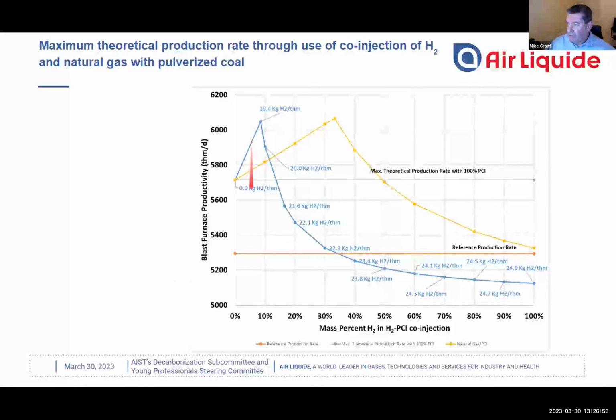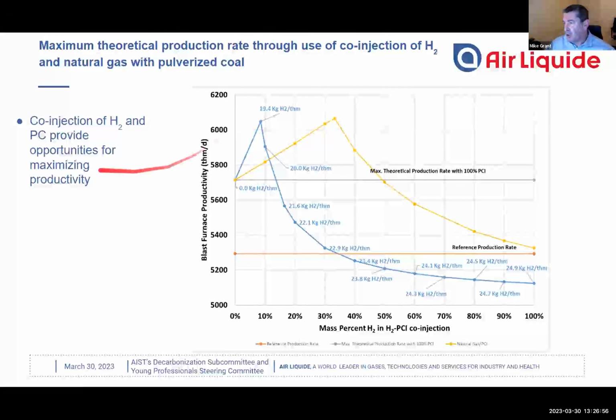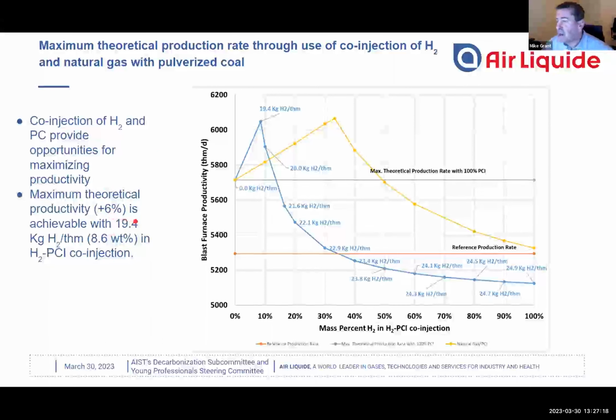However, there is a productivity benefit, and you see if we co-inject PCI with hydrogen, we can actually increase the productivity of the blast furnace beyond the limitations of the original operation with PCI. So if this is the maximum theoretical production rate with PCI, and we mix a little bit of hydrogen in there, we can actually get another 6% increase in productivity on a theoretical basis. The same effect is also true with natural gas, although you need a higher amount of natural gas in order to get this maximum productivity benefit. But nevertheless, there are some benefits to co-injecting hydrogen and or natural gas with PCI.